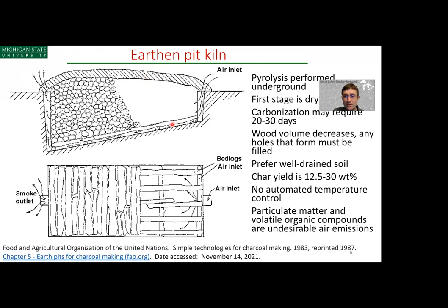This type of kiln system prefers a well-drained soil. You certainly don't want a lot of water down here, so that's important. Char yields are quite variable using this type of system, from as low as 12.5% weight on biomass to as high as 30 weight %. There's really no automated temperature control here. Of concern, which we'll talk about in a subsequent slide, is the emission of particulate matter as well as volatile organic compounds. So if you're going to perform earthen pit kiln pyrolysis, be aware those emissions are occurring, and if you have neighbors nearby, there may be some nuisance odor complaints.